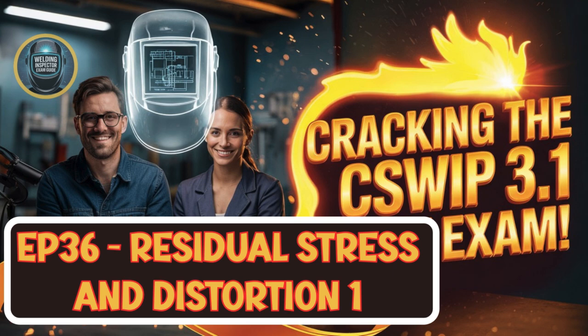Okay, what about more serious failure modes? Well, residual stresses can significantly increase the risk of brittle fracture. Brittle fracture. That sounds bad. It is. It's a sudden catastrophic failure with little warning. In certain conditions, like low temperatures, the tensile residual stresses add to any applied stresses from the load. If the combined stress reaches a critical level at a small flaw or notch, bang. Is that common? It was a major issue historically, like with the Liberty ships in WWII failing in cold seas. It forced a huge leap in understanding fracture mechanics and material selection. Today, designs in sensitive applications account for it, often requiring materials with high toughness, especially at low temperatures, and sometimes mandatory stress relief. Wow. Okay, any other major ones?